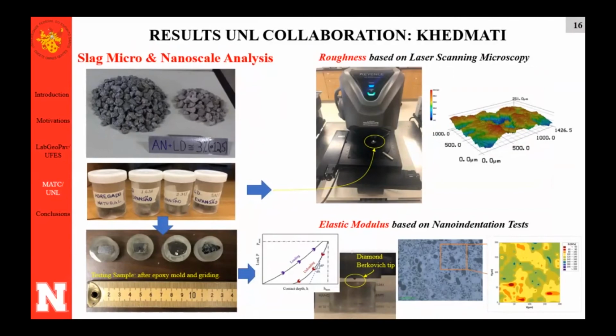So with the collaboration of one of the students from Dr. Kim's group, Mrs. Khedmati, we did some roughness analysis based on laser scanning microscopy, and also elastic modulus evaluation based on nano-indentation tests. So we took samples, we polished, we ground the material, and we did this test for nano-indentation, and we also did this evaluation with the microscopy to get the parameters and try to correlate with the unknown questions that we had from the projects in Brazil.